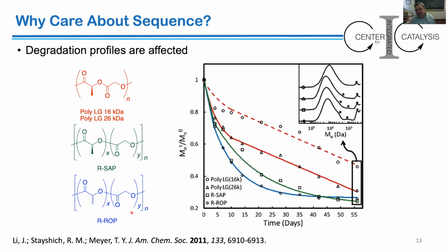It's the most amorphous. And so oftentimes that's the case when you have a crystalline polymer that can organize itself. So these with either the stereoregular polymer or an alternating polymer, as in this case, you see stiffer polymers that then have a harder time to degrade because the crystalline polymers have a harder time for the water to get to the esters to hydrolyze.